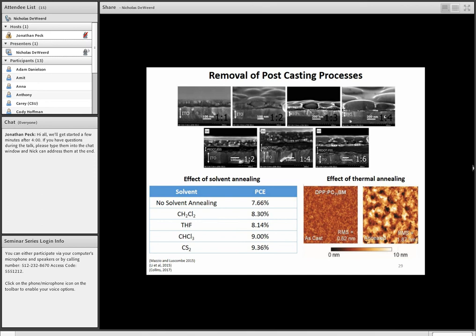Most people anneal for like 10 minutes at 90 degrees or 100, and then optimize in that range. And for this device, annealing did improve the efficiency, but more importantly, you can see the morphological changes. So you can see the roughness has gone up, and that's because the crystalline domains have become larger, which is giving rise to higher conductivities and higher efficiencies. The problem with these things is